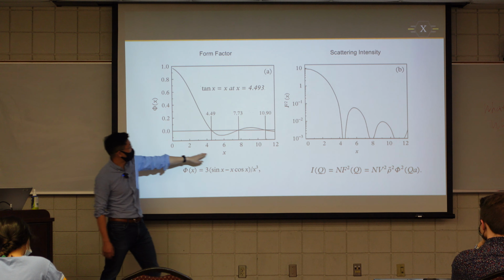So in the textbook, it gives an example. Let me jump into that. I'll show you a real example. So this is SAXS, small angle X-ray scattering data for a dilute suspension. We know why it needs to be dilute, because we want to look at the form factor. So that's about 0.1% volume of polystyrene sphere. This sphere, I believe, is 100 nanometer in radius R.